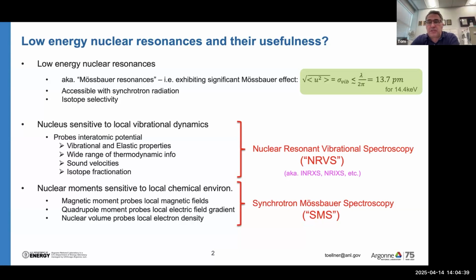The other technique is Synchrotron Mössbauer Spectroscopy. This exploits the nuclear moments of the iron isotope, such as the magnetic moment, to probe the magnetic ordering or spin state of the material. A quadrupole moment allows you to be sensitive to electric field gradients that are related to the bonding environment of the iron atom. And also the nuclear volume probes the s electron density, and so is sensitive to any changes in valence or oxidation state.